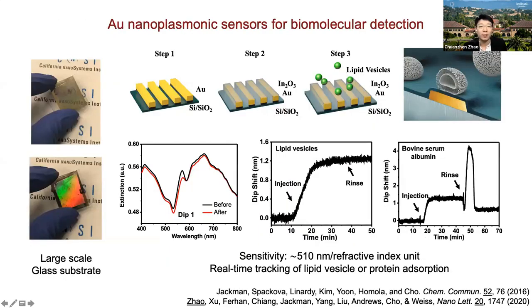Now with this in mind, we can go back to the fabrication. We can use the HD DVD as a mold and make the PDMS stamps, and use the PDMS stamp to pattern for the chemical lithography. And we can also pattern the gold nanostructure over centimeter scale on glass. The plasmonic peaks of the gold nanoribbons will shift in environments of different refractive index. And we have shown that those gold nanoribbons have a sensitivity around 500 nanometers per refractive index unit.